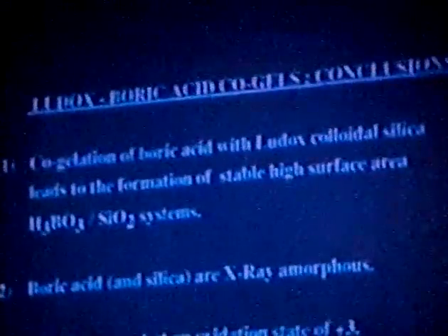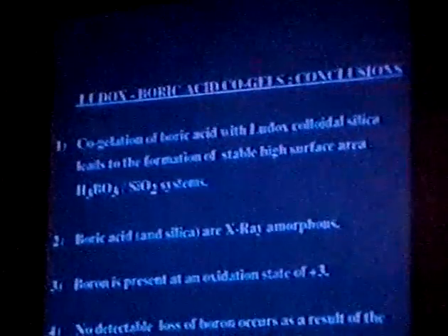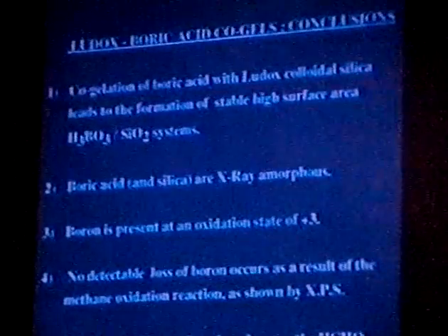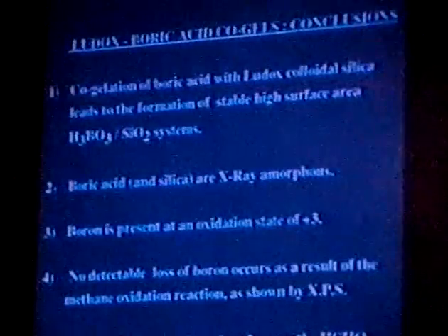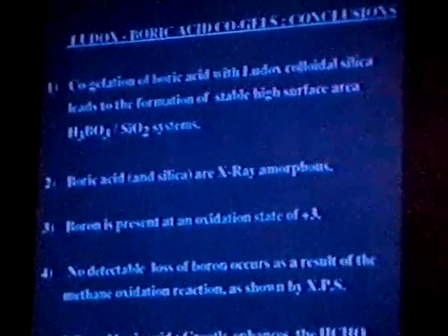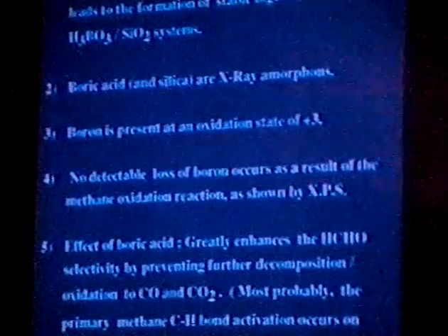Now the conclusions for the Ludox boric acid co-gels are that the co-gelation of boric acid with Ludox silica can lead to the formation of stable, high surface area boric acid silica systems. The boric acid co-gels and the silica Ludox support prepared by the gel method were X-ray amorphous. Boron is present at an oxidation state of +3, and we did not observe detectable loss of boron when we did XPS on the catalyst before and after the reaction.